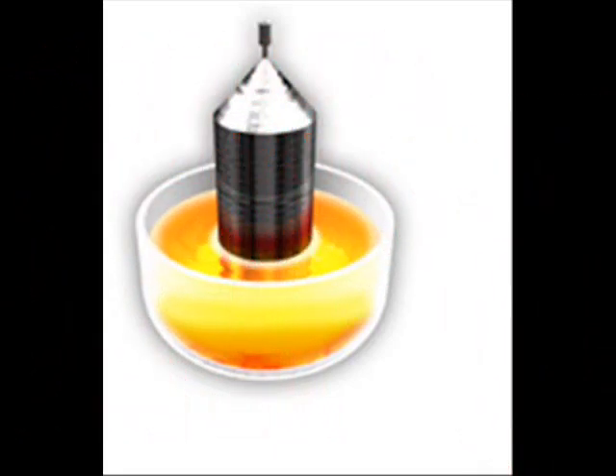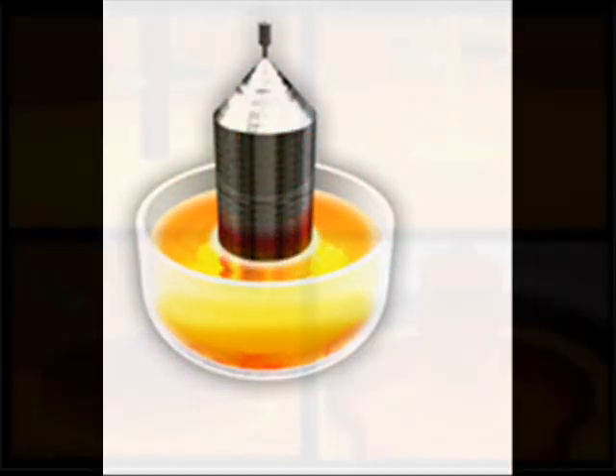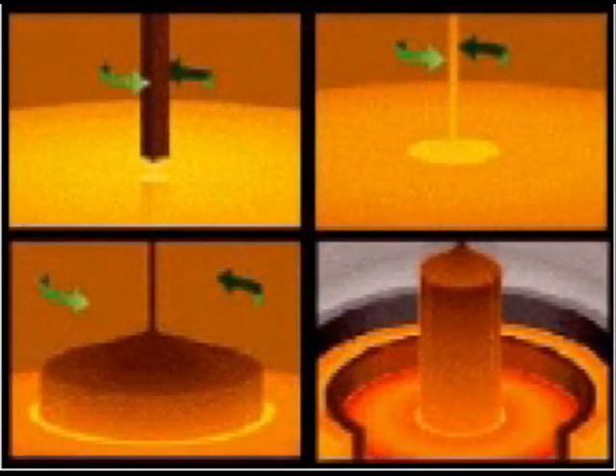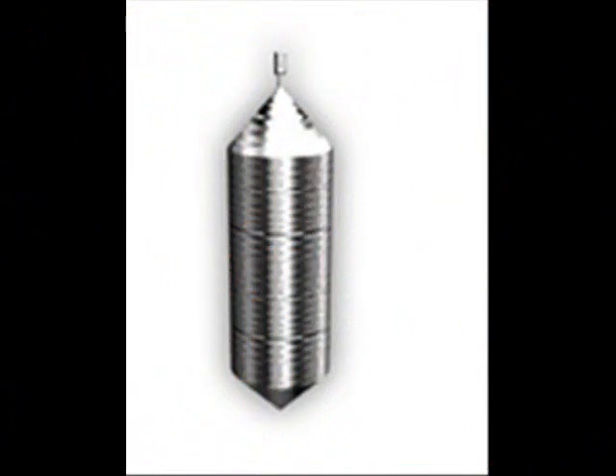In the CZ method, polycrystal silicon nuggets are placed in a quartz crucible, which is set in a graphite crucible surrounded by graphite heaters in the crystal pulling chamber. These nuggets are melted by heating in an inert atmosphere under vacuum and then pulled slowly using a seed crystal.